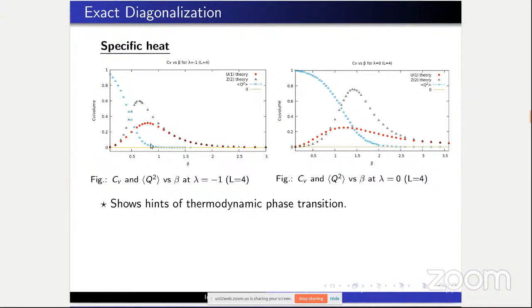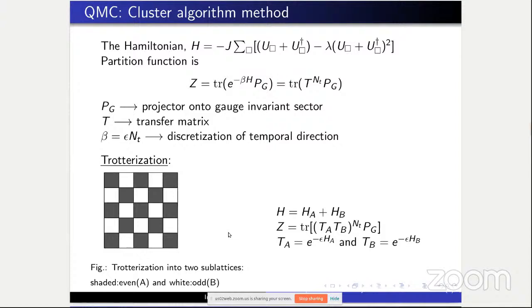Now this is a specific heat and average charge curve versus beta graph obtained using the exact diagonalization method, and this graph showed some initial hints of a thermodynamic phase transition. Now the cluster algorithm method. First, we have divided the lattice into two sublattices: the even or A sublattice, the shaded plaquettes, and the odd or B sublattice, the white plaquettes.